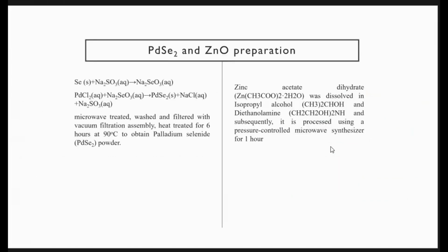And this is the synthesis method. We used selenium and sodium sulfite, and we formed a selenium salt. And then we incorporated palladium chloride to that selenium salt, and we kept it in the microwave assisted technique. Finally, we got some byproducts, and we removed them through centrifuge. We washed and filtered, and finally we did annealing. The same procedure we followed for zinc oxide synthesis.